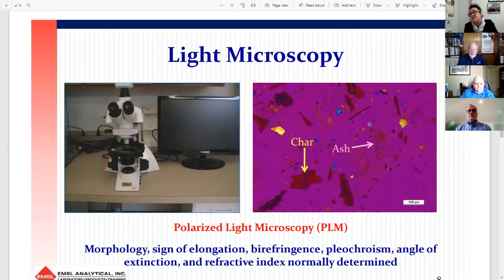Ash is difficult for any method, but with the training and with the right sampling, it can be analyzed easily by PLM. In this picture, the yellow and the blue particles, those are quartz. So you can see the entire constituency of the sample on that slide and what else is in the sample other than char and ash, to have an idea of how much char and ash there would be, because this is the main method that is used to derive the concentration, either by visual area estimation or count or whatever method is applicable to produce a numerical result.